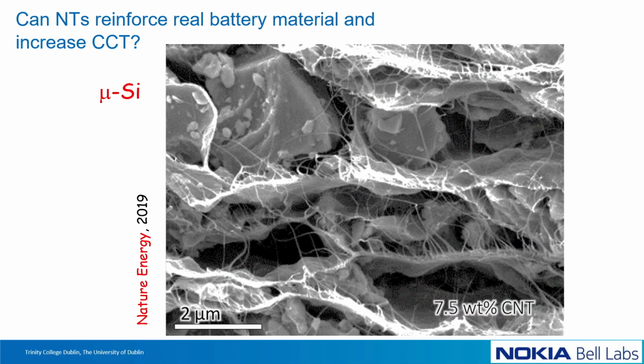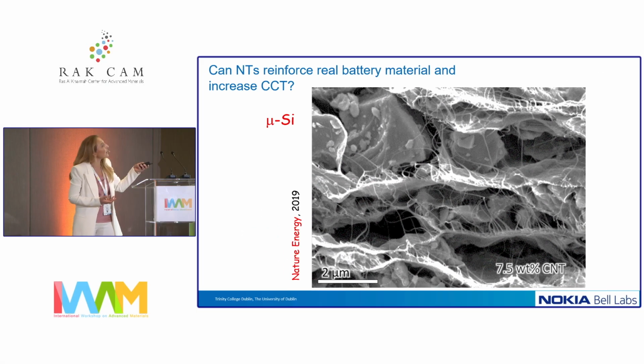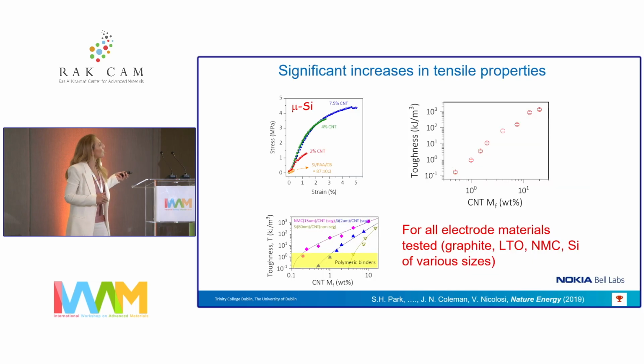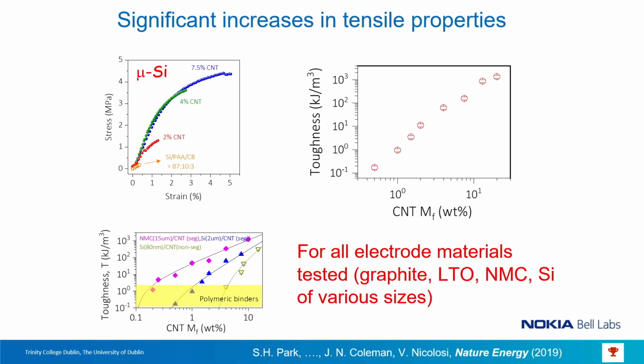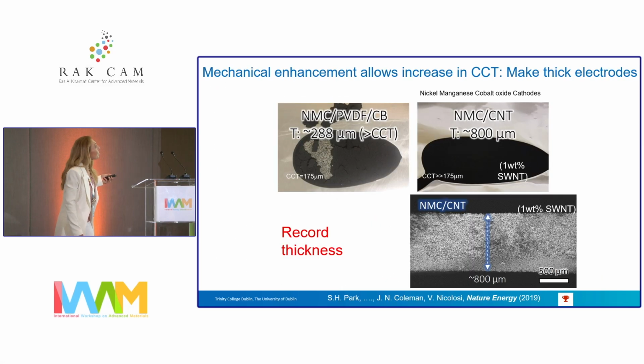We did that, and we realized that if you can balance the mass loading of carbon nanotubes, you can still achieve the same segregated networks we discussed about. But this time, these blankets were not formed by 2D MXenes, but 1D carbon nanotubes. And the results were quite outstanding, actually. In the same case, we could massively improve the toughness of the electrode with a very minimal amount of carbon nanotubes. So this actually worked for silicon, but also for many other standard electrode materials like LTO, NMC, which are on the cathode part.